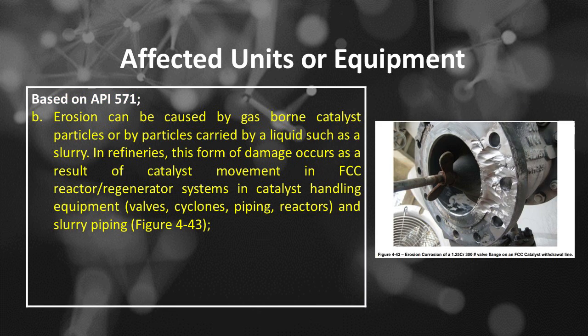The second is that erosion can be caused by gas-borne catalyst particles or by particles carried by a liquid such as a slurry. In refineries, this form of damage occurs as a result of catalyst movement in FCC reactor/regenerator systems, in catalyst handling equipment, valves, cyclones, piping, reactors, and slurry piping, see Figure 4.43. Figure 4.43 is erosion-corrosion of a 1.25 Cr 300 valve flange on an FCC catalyst withdrawal line.